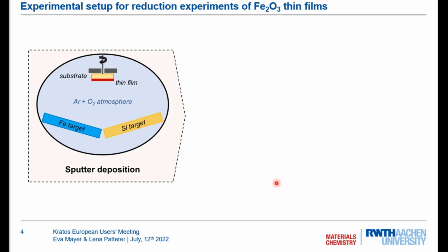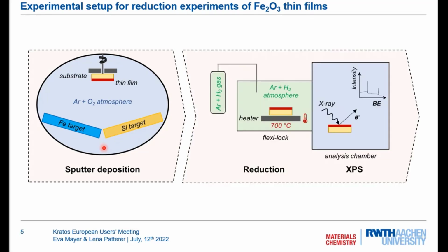So we say we create a model system, and therefore we use sputter deposition to obtain thin films that consist mainly of iron oxide, but also some small doping concentrations of our tramp element. And in this first example, it was silicon that was added into the deposition. And afterwards, we do the reduction, and this is also kind of a model system of the hydrogen-based direct reduction as it is done in industry.